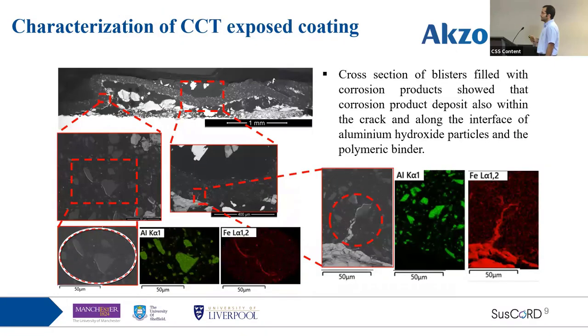So I think for the samples that were exposed to the cyclic corrosion test, the failure has happened due to the crack initiation and propagation, which allows the environment to reach the metallic substrate. But then when the corrosion starts, it will lead to blister formation. As you can see here, I think there are two blisters that are connected together and are filled with corrosion product. At this stage, we can also see cracks start to form within the coating at the periphery of the blisters, and these cracks are filled with corrosion product.